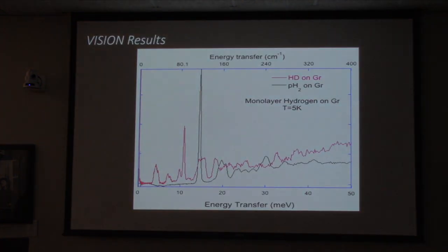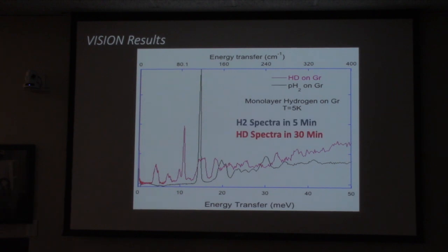Here's that same experiment that I showed you before with the ortho to para conversion. The other one was done at ISIS. This was done at VISION at the SNS. So there we go. These are all with para hydrogen on graphite. This turns out to be HD on graphite. Remember how long I said that it took in the past, so let's make a comparison. This spectrum for H2 took 5 minutes at VISION, and the HD one took 30 minutes as compared to 3 days. So I think we've made some steps forward.